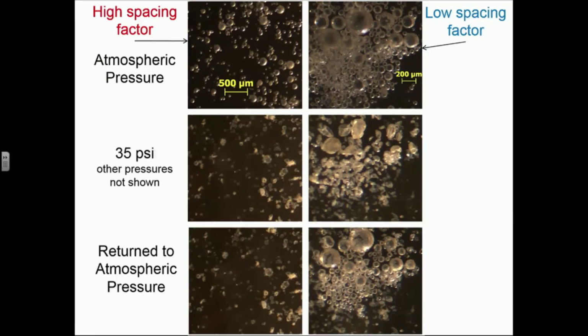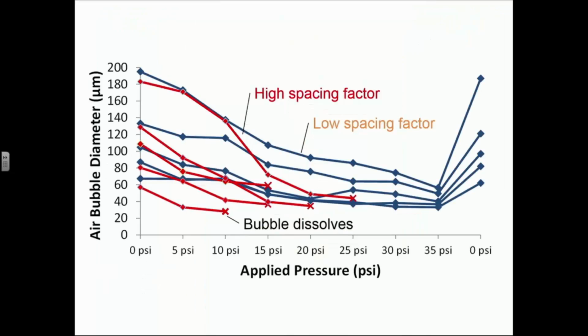But the important point about this slide is that the bubbles with low spacing factor, bubbles close together, have a totally different performance than bubbles that are far apart. These mixtures are the same. They have the same dosage of air entrainer. Actually, the dosage of air entrainer is a little bit different on the one on the right. This just happens to be where we looked at a cluster of bubbles. This just happens to be where we looked at bubbles far apart. Totally different performance. Now let's show it graphically.